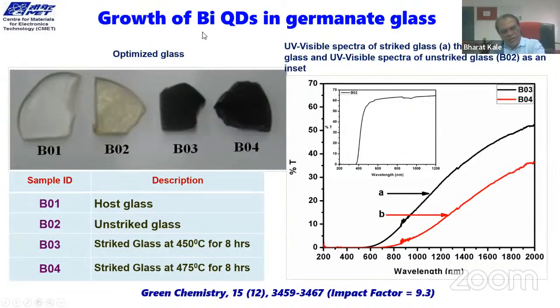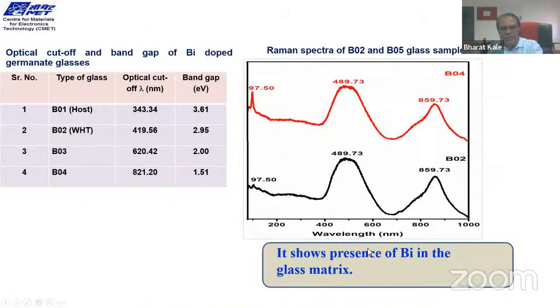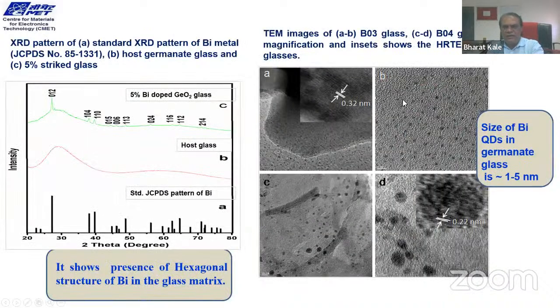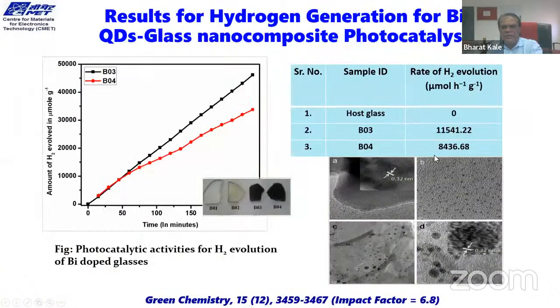Then we also have bismuth in the glass, and you see the absorption is from 600 nanometers towards the higher region when we have quantum dots in it. This is without quantum dots, and after the growth of quantum dots, we can see there is a huge shift in the visible region, and that helped a lot for hydrogen evolution. The Raman we have taken because Raman clearly shows the formation of bismuth in the glass. TEM clearly shows very tiny nanoparticles of 4 to 5 nanometers of bismuth, very uniformly distributed in the glass. And we observe a much higher hydrogen evolution, 11,540, for these bismuth nanoparticles. The smaller the particle in the glass, the higher the hydrogen evolution, which we observe.